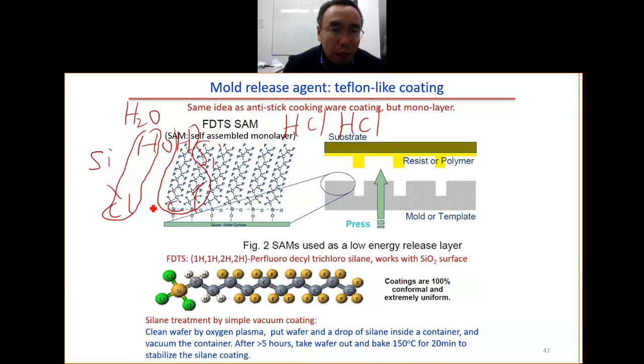So you have this oxygen here. They have this silicon oxygen silicon that you can see here. So effectively, you form 2 HCl molecules to take away the chlorine. Then you have the oxygen bond. So normally you clean the wafer. Then you put a drop of the silane on the wafer. This silane is a liquid. You put a tiny drop, maybe a microliter, inside the container and vacuum the container. After several hours, you take it out, you do the baking, you get a very high quality coating. And you make the surface very hydrophobic.